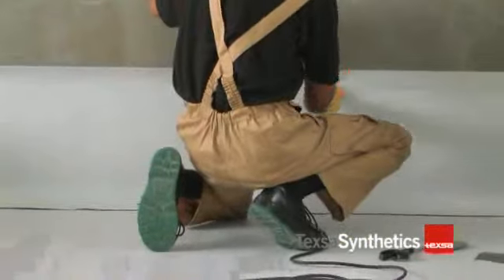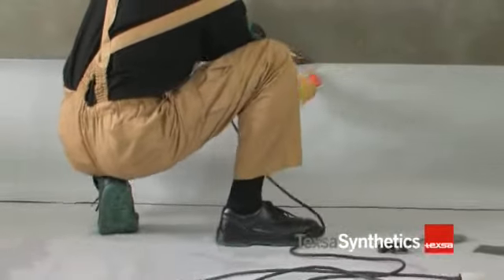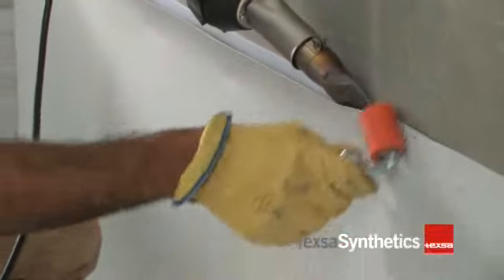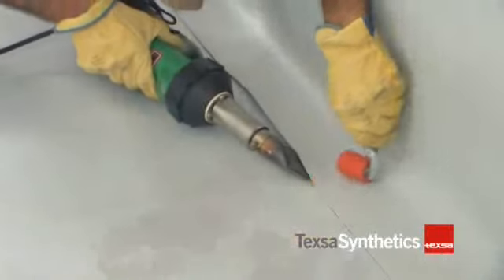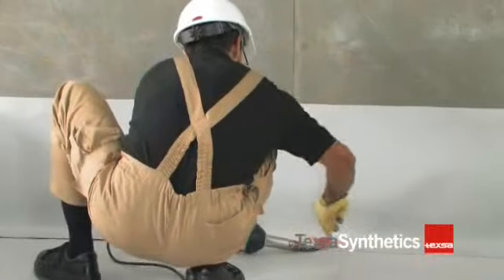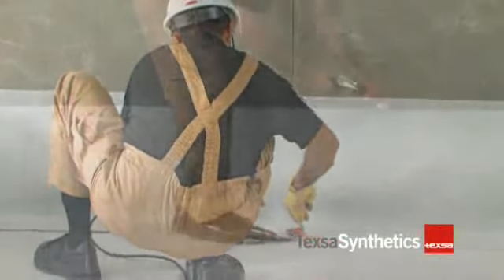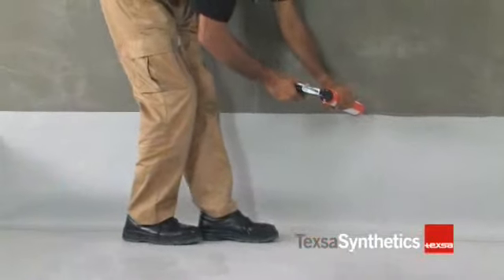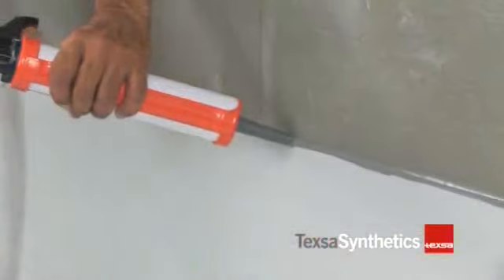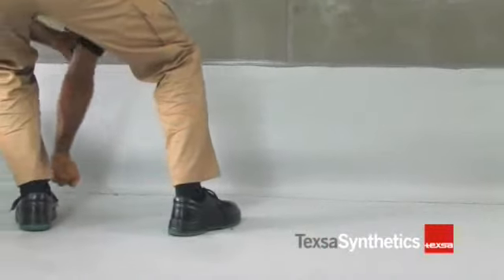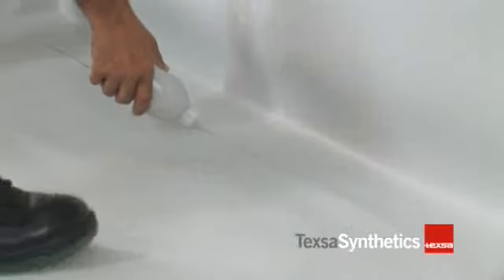This termination bar must be previously fastened to the support structure with lag screws. Press with the roller to weld the membrane to the laminated termination bar. Make the joint with the roofing membrane, leaving at least 10 centimeters of overlap. Then weld the joint following the regular procedure. For greater precaution, apply a bead of polyurethane mastic on the top of the termination bar. Check the joints with a blunt screwdriver. Finally, apply liquid PVC along all the seams and joints.